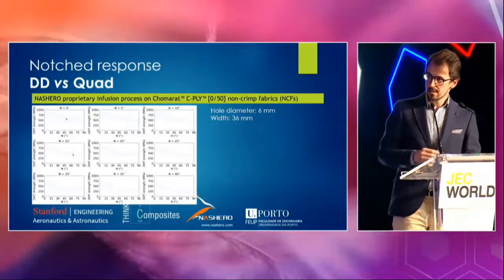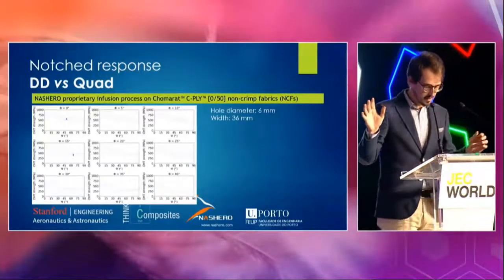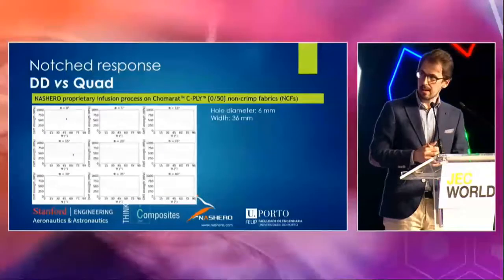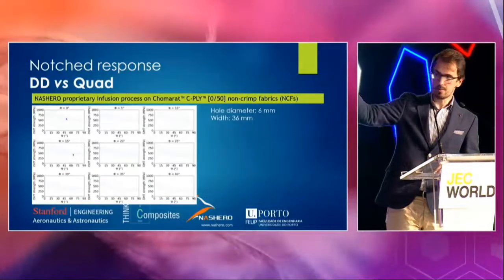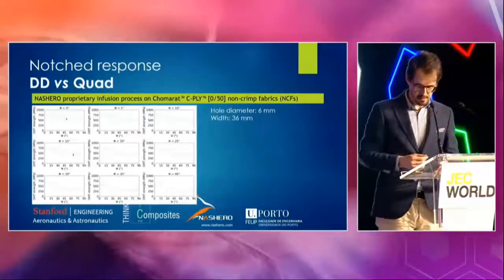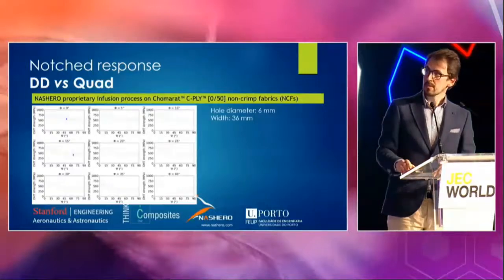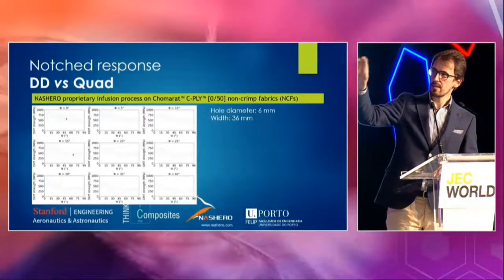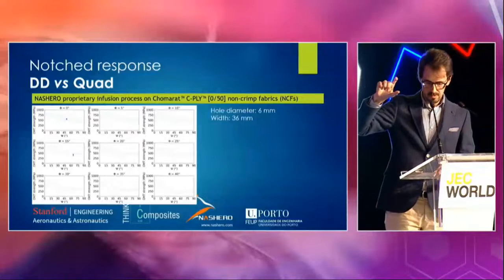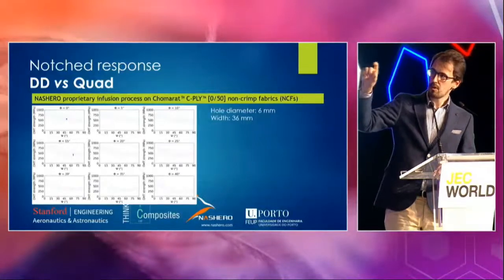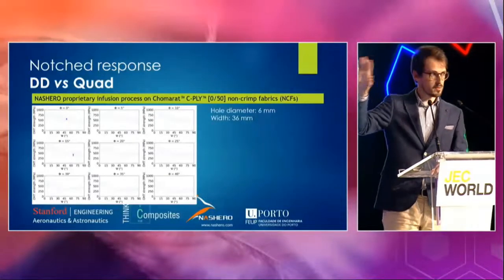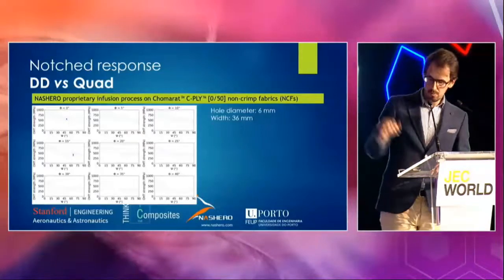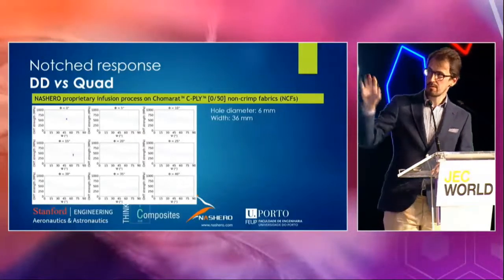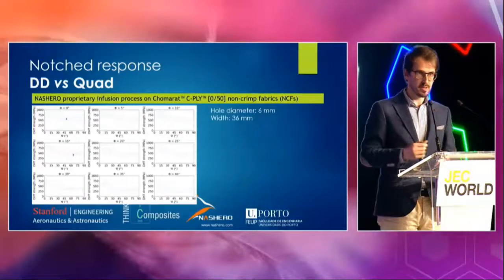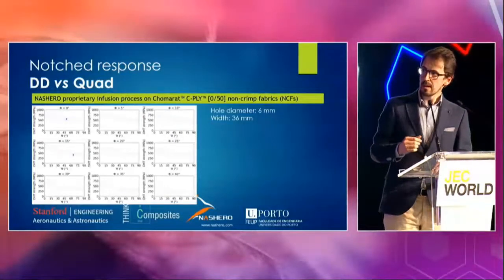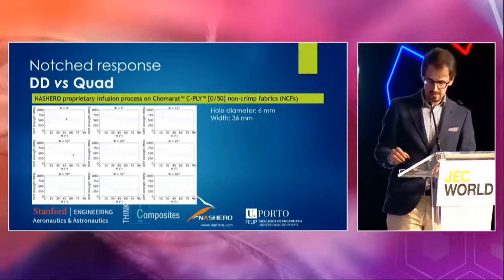Now, what is the exercise then that we can do? Let's take different phi angles for the first angle ply, and then you can vary the psi angle for the second double. And what I'm plotting there is essentially the band for the notched strength of those laminates on an open hole specimen with a hole diameter of 6 millimeters and a width to hole diameter ratio of 6. And you can see how the predictions come out.